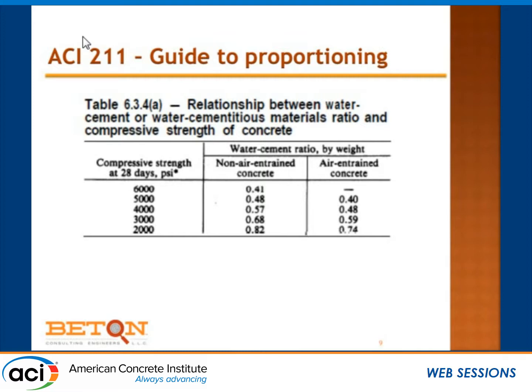And it says that for 4,000 PSI concrete, for non-air-entrained concrete, I need a water-to-cement ratio of 0.57. Now, maybe I need 0.40 for another reason, permeability, let's say. But we start to run into some difficulties if there is a perceived conflict between those two values. And where does all of this come from?